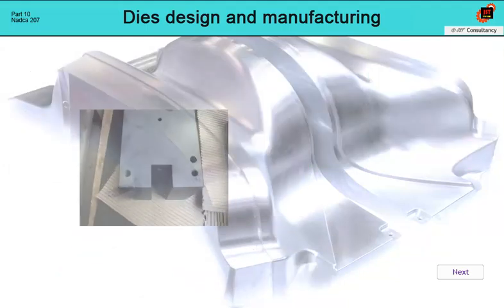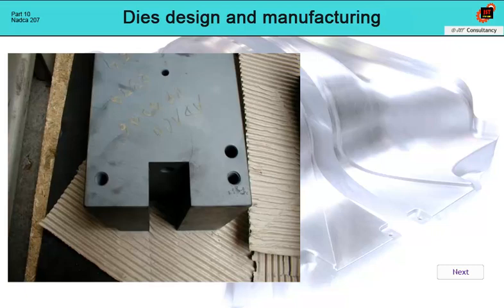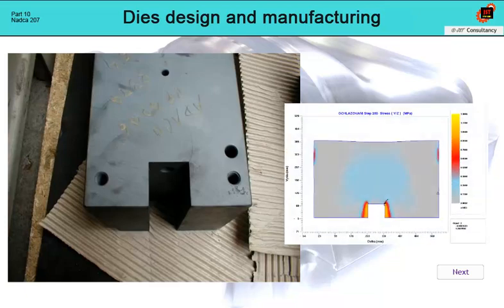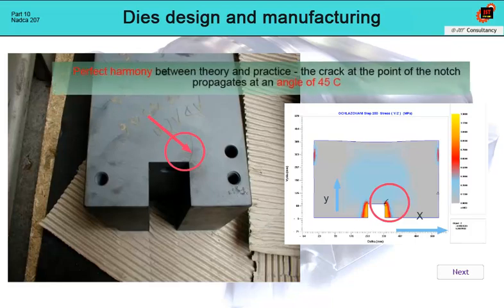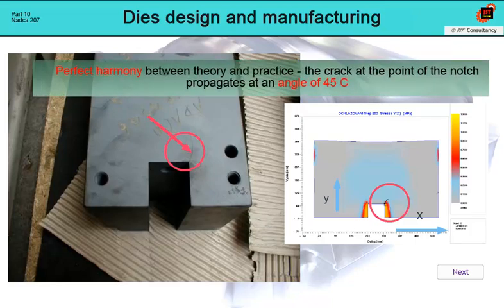On this picture, we are already getting to practical examples. In the theoretical model of the impact of the notch on stress, it was seen that the crack spreads from the sharp corner of the notch at an angle of 45 degrees further into the body. This is a consequence of the superposition of tensile stresses in the x direction and in the y direction. In a practical example, it can be seen that the agreement between the model and reality is very accurate.